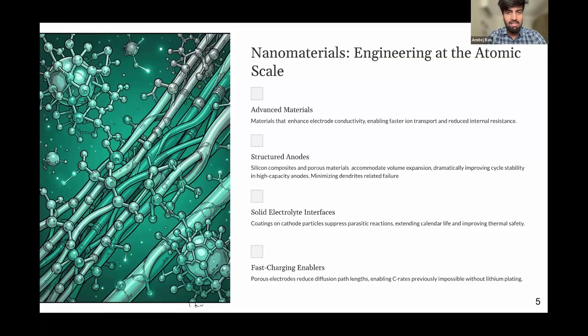So the anode materials, the cathode materials and the electrolyte materials have to be such that they have certain specific properties. When we talk about electrodes, number one, we need enhanced electrode conductivity, which is electronic conductivity and ionic conductivity. It also needs reduced internal resistance, which means when the reaction is happening, the kinetics should be much faster, and the temperature rise shouldn't be as much, because if the temperature rises, then there is a safety risk.